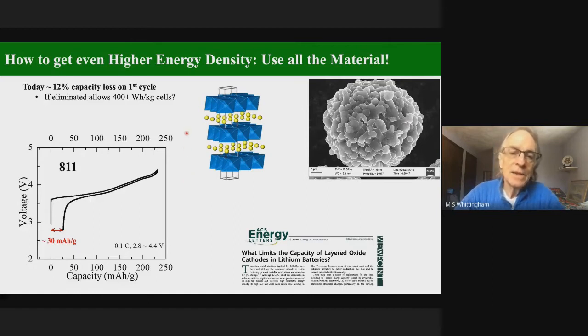So a challenge on this material is when we charge it up, and now we're working on the 811 material. When we charge it up, here's the charging curve. You can see we're getting to about 230 milliamp hours per gram. We discharge it down here. You notice we lose about 30 milliamp hours per gram on the very first charging cycle. This is between 10 and 20% of the capacity. We have to recover that.